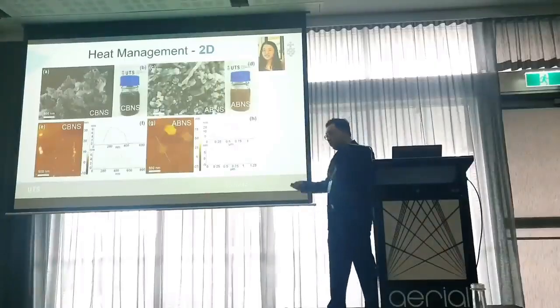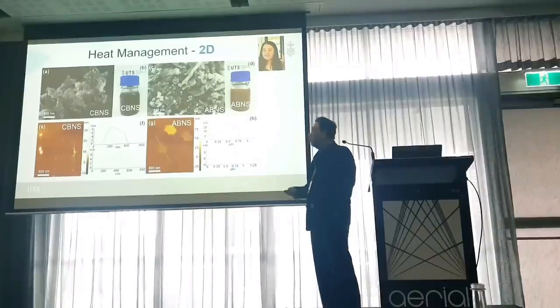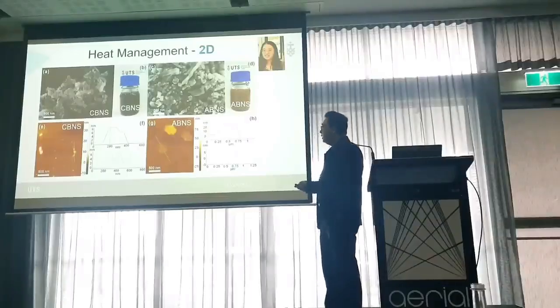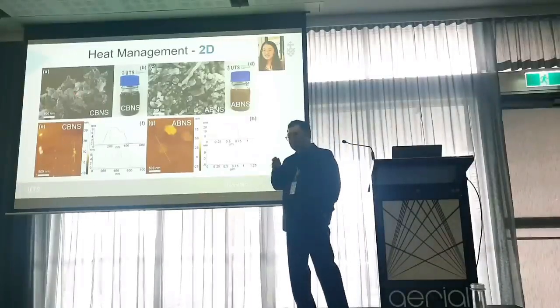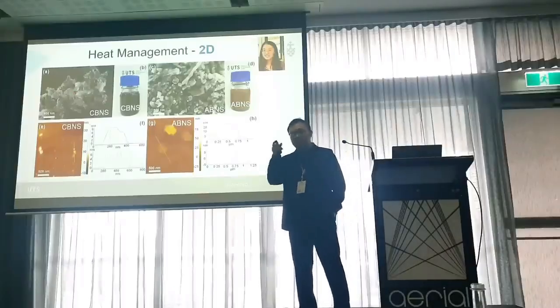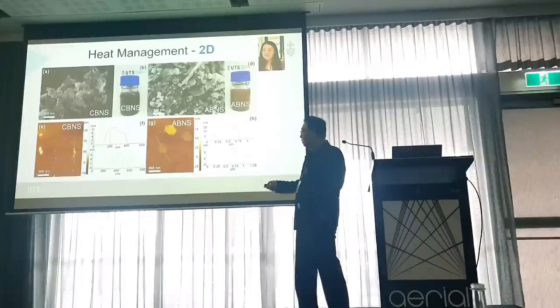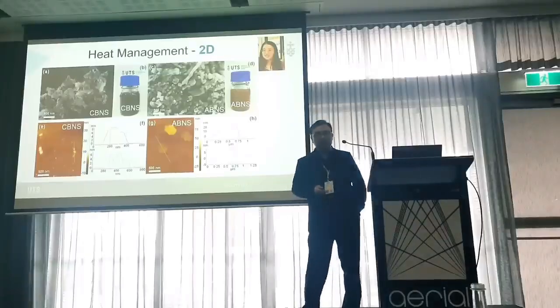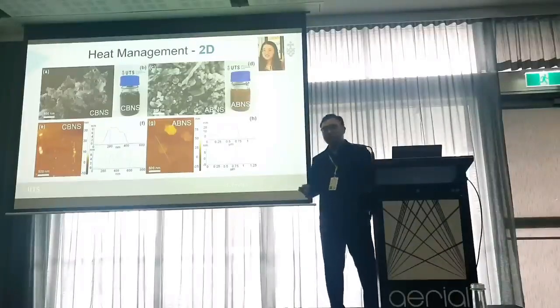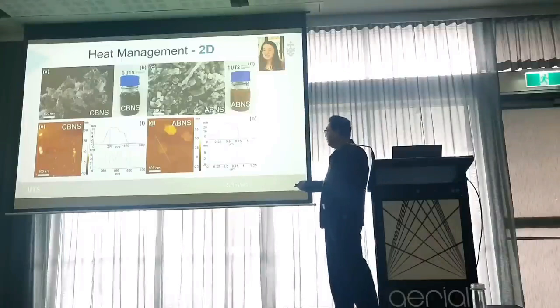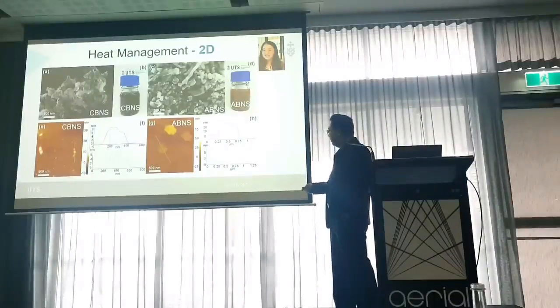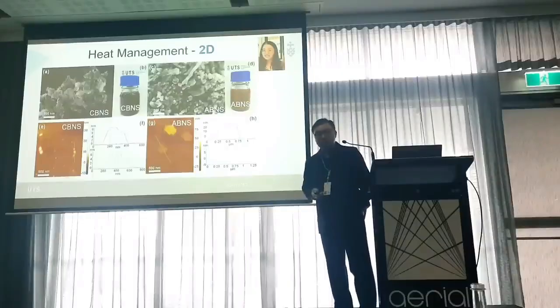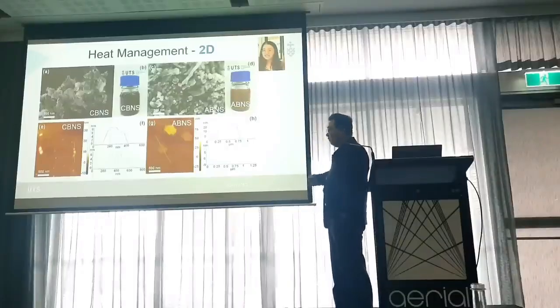And then we wash these materials, disperse them in water, and characterize them by SEM. As you can see, the crystalline boron nitride nanosheet is relatively smaller and has a higher aspect ratio. The thickness is about 7 nanometers, while the diameter is about 300 nanometers. In contrast, the amorphous boron nitride nanosheet has a thicker thickness, about 20 to 30 nanometers, while the diameter is about 500 nanometers. So the crystalline boron nitride nanosheet has a higher aspect ratio.